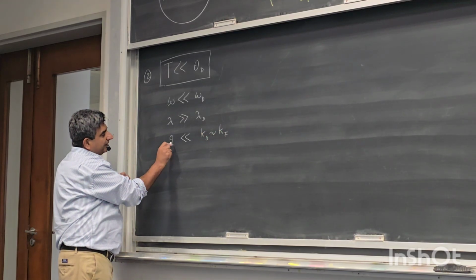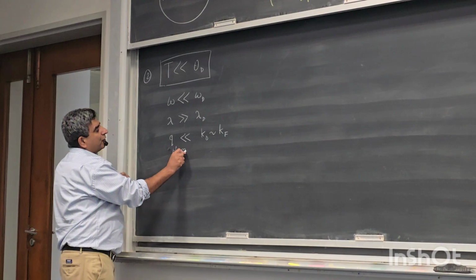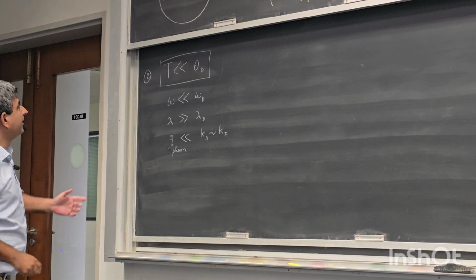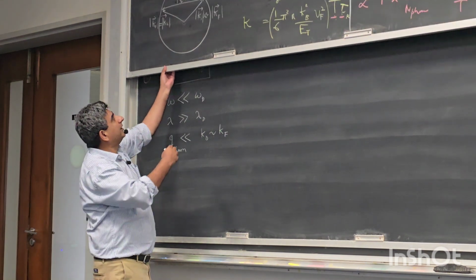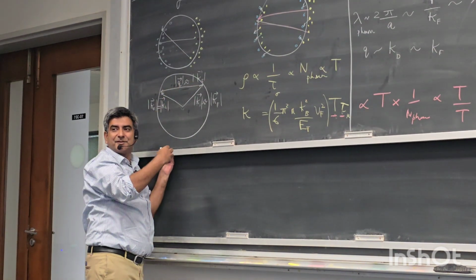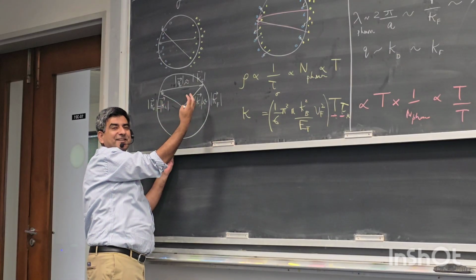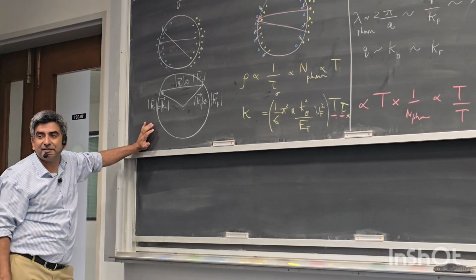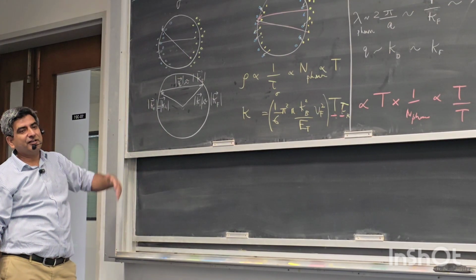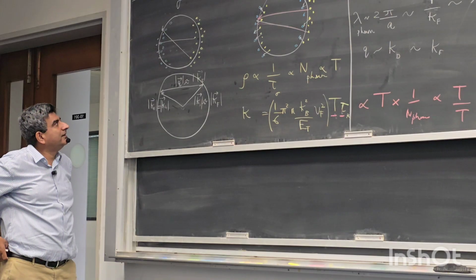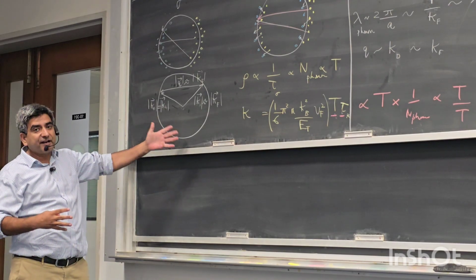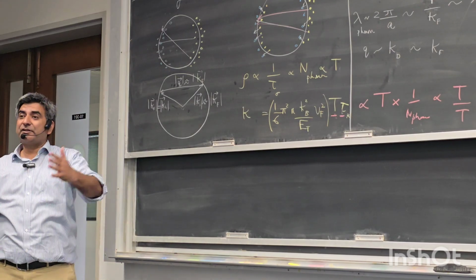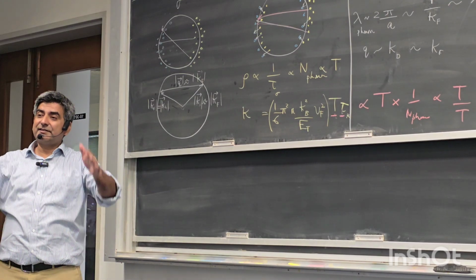So the wave number of the phonon, or the length of the momentum vector of the phonon, is much smaller. You do not have the luxury of these long wavelength phonons in the system to affect this transition from the right to the left side of the Fermi sphere. Therefore, the electrical conductivity goes up, which means that the scattering rate becomes longer, the electrical conductivity is increased and the resistivity drops.